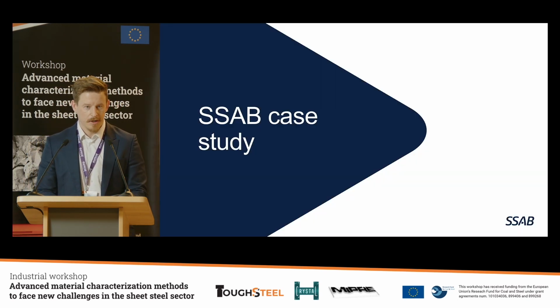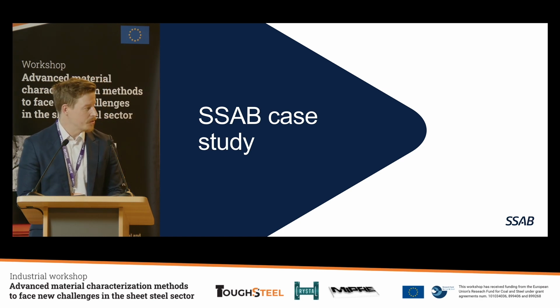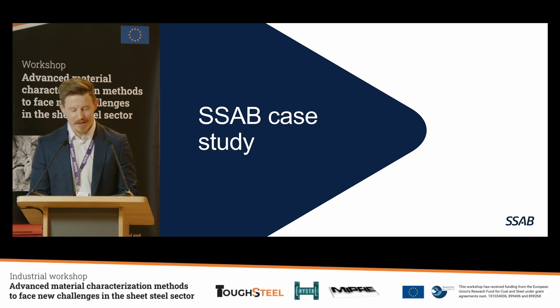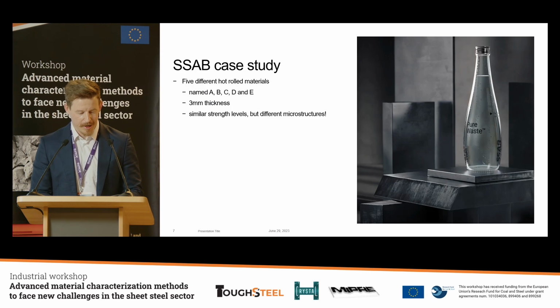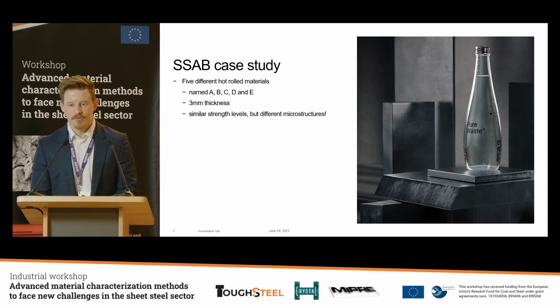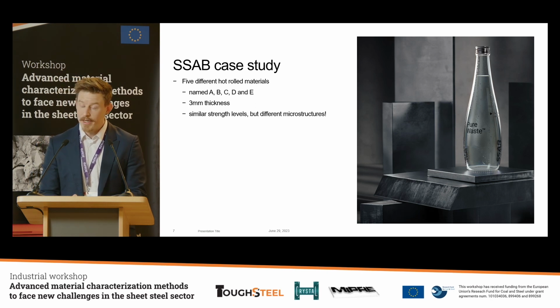But I think we should go into our case study, and we selected 5 different hot-rolled materials. They are in 3 millimeter thickness, and the idea was that we will select very similar strength levels for all the materials, but very different microstructures in order to make things really interesting.